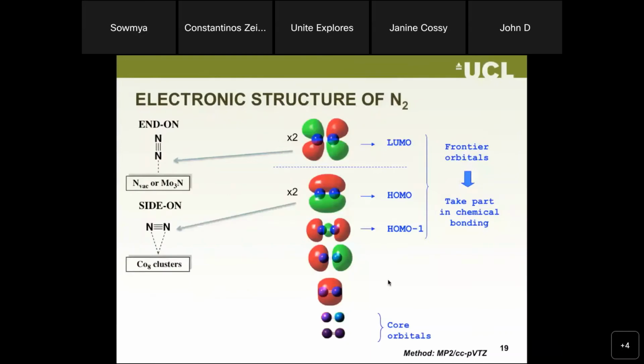The side-on adsorption is due to these filled orbitals, so a donation of electron density from this filled orbital into the empty d orbitals of the cobalt.